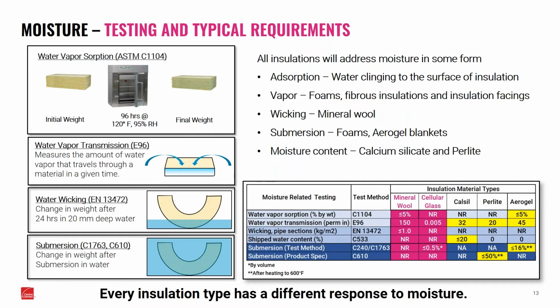Then finally, submersion. And again, this is going to ASTM C610, that's for expanded perlite. That allows up to 50% moisture content. But again, that's after heating to 600 degrees Fahrenheit, and that's after it's been heated and soaked for long periods of time. So again, none of these products are going to be waterproof at those temperatures.